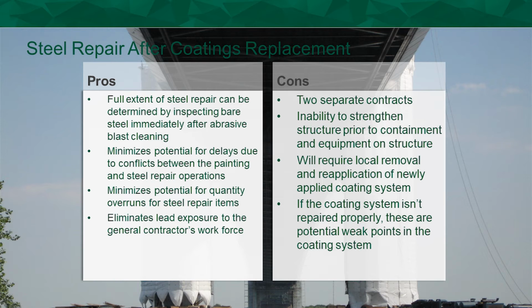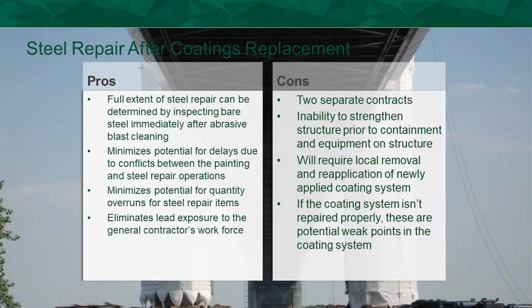So now the paint contractor is going to have to come back and adjust and repair those areas where damage occurred. So what happens? If they don't repair it properly and do the surface preparation like they did originally in the 3 coats of paint, that's where you have your potential weak points. That's where you have your possible failures that can occur on that structure much quicker than the structure should last. If it's a zinc epoxy urethane system and you're looking for 25 years, in those weak areas, like we talked about just a little bit ago with the section loss, you could lessen that down to maybe 5 years, again, because of not doing it properly.